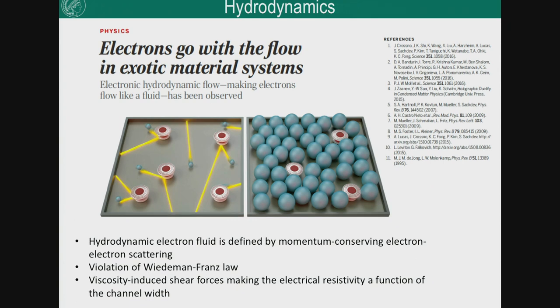we still believe that this hydrodynamic flow maybe plays an important role in these compounds which show topology, because in 2016 there were three papers published at the same time, two on graphene and one on palladium cobalt oxide, PdCoO2, from Dresden, by Philip Moll and Andy Mackenzie. They claim that they have found materials where the electrons don't flow like a Drude gas, they flow much more correlated, like a viscous liquid. And there were different experiments for how they did this, because this is like an electron getting scattered on the nucleus. This is a symbol here for the nucleus, or the electron simply flows through the crystal. One was thermal transport, which shows a violation of the Wiedemann-Franz law, showing that the phonons are decoupled in some sense from the electron scattering.